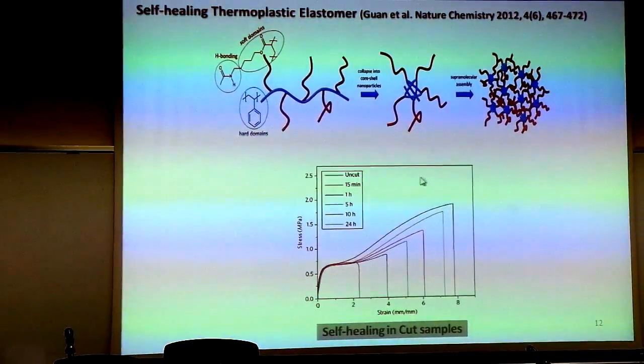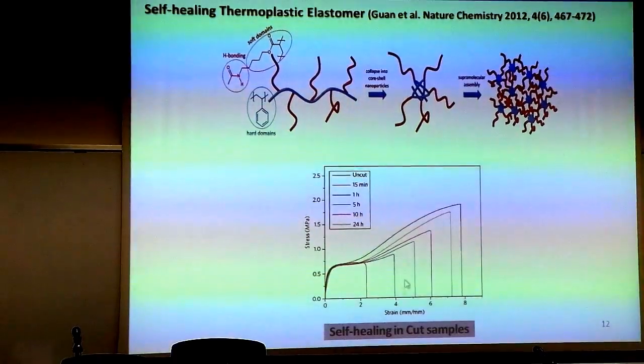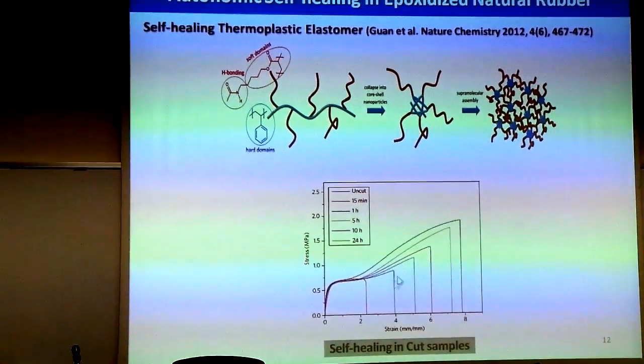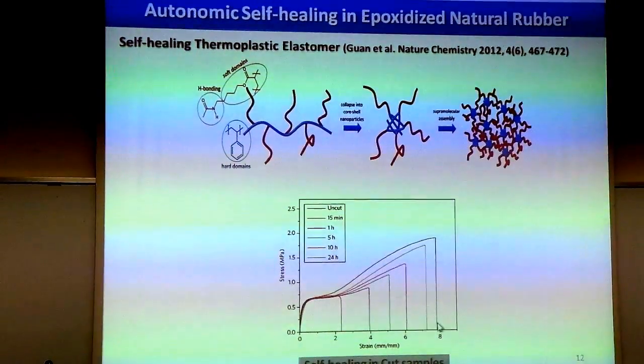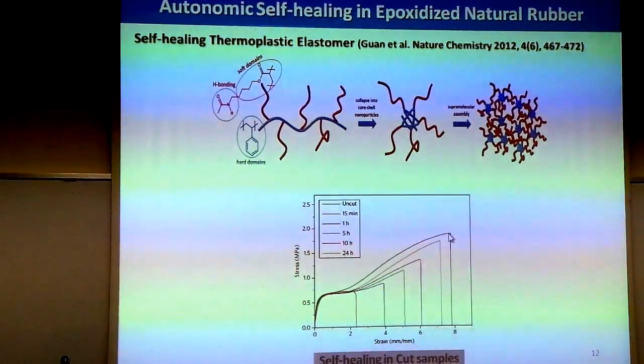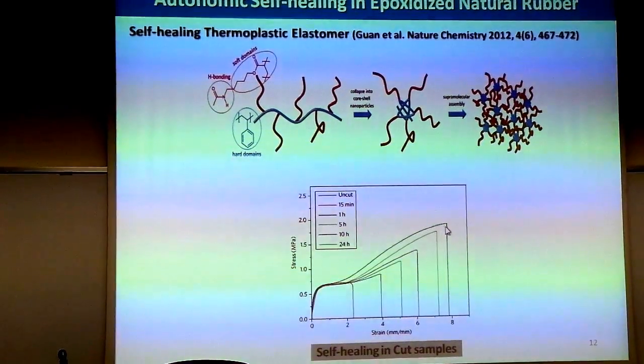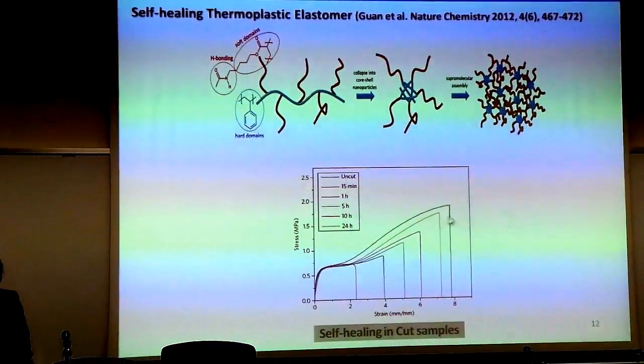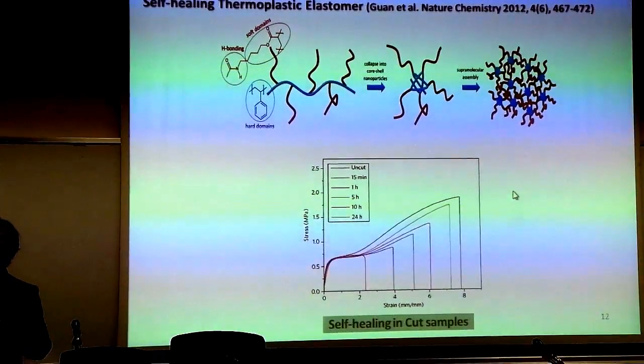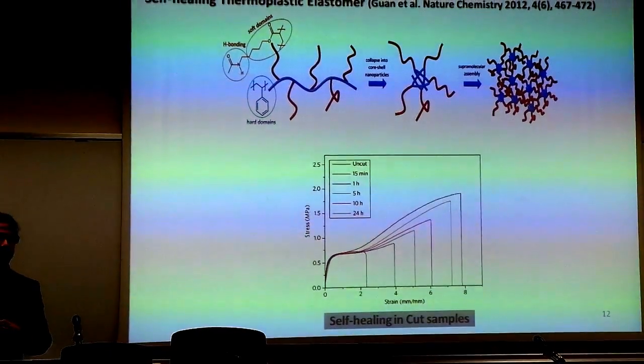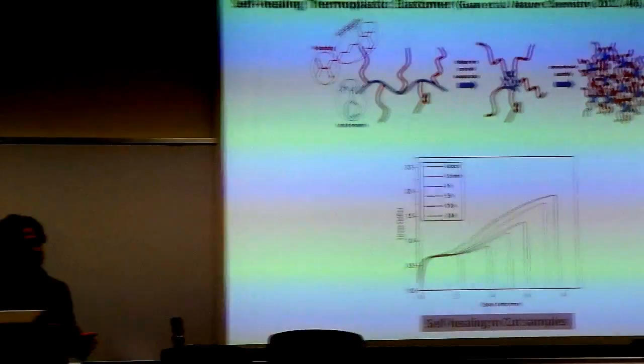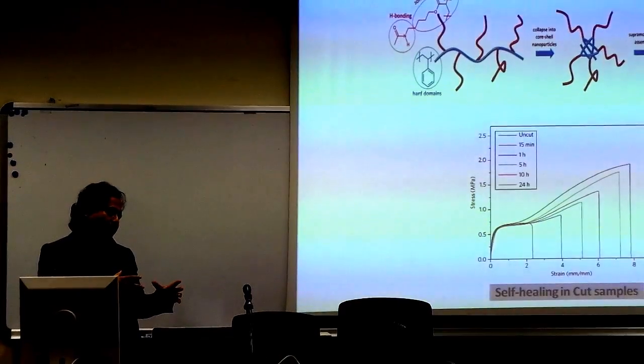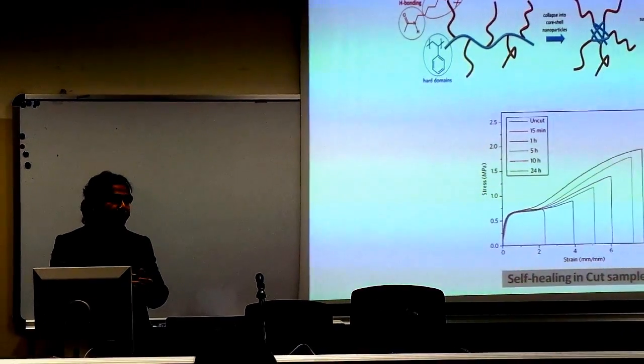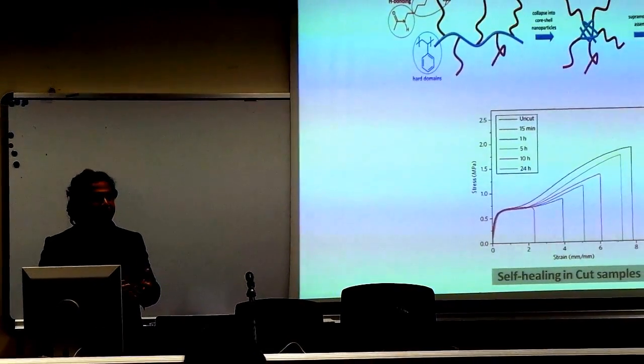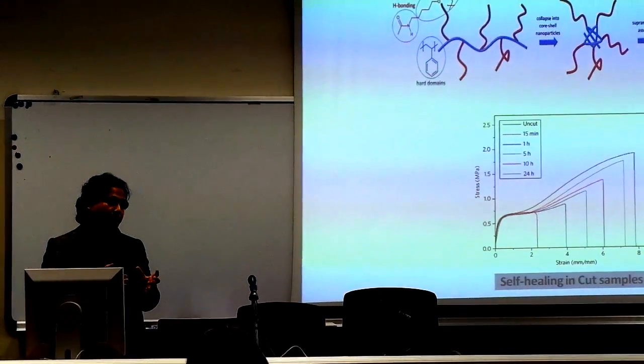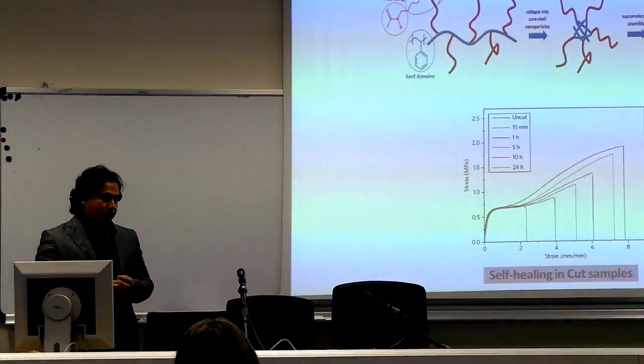And they studied in the same manner the self-healing behavior of the rubber by cutting in the middle, and after a certain period of time, they found that the material can recover almost 80% of its virgin strength. However, I should inform you that most of the work on self-healing elastomer was done using supramolecular chemistry, but no work has ever been reported on the self-healing behavior of conventionally synthesized elastomer.